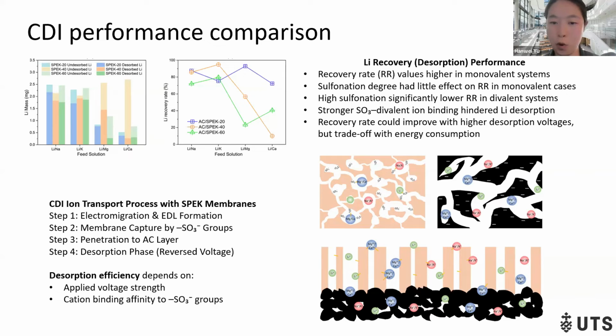And finally, most adsorbed cations leave the active carbon and re-enter the membrane. Partial bonds between sulfonate group and cation break, and then cations are released into the effluent. But some cations rebind in the membrane, so they are trapped in the AC membrane electrode. And we found the desorption efficiency can depend on the applied voltage strength and the cation binding affinity.